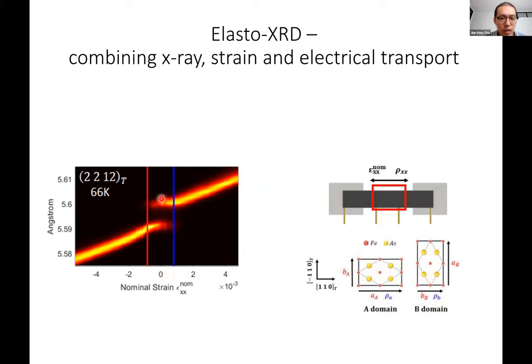And then you can see that as you increase strain, the two diffraction peaks gradually become one diffraction peak. The intensity of one peak is suppressed and the intensity of the other peak increases. Now this is basically aligning domains. And then when you further apply the strain, you can see that the diffraction peak starts to move in two theta, or d-spacing, and it moves linearly with the strain you apply. So now we're distorting the crystal.